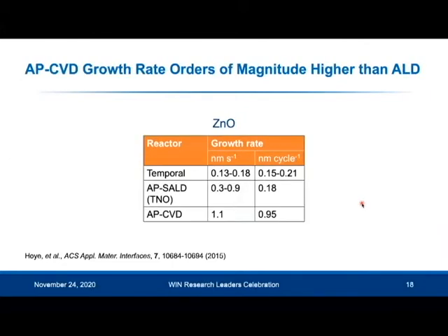And you see that here, this is for the example of zinc oxide with conventional temporal ALD. So that's your standard ALD reactor where you put precursor 1 in step 1, then you purge, then put in precursor 2 in step 3, where you separate the two precursors in time in different pulses. Then you have a very low growth rate between 0.1 and 0.2 nanometers per second, whereas by APCVD, the growth rate is an order of magnitude larger. So what that means is that instead of taking 1 hour to grow 10 nanometers of your oxide, you can complete the deposition within a couple of minutes in open air.